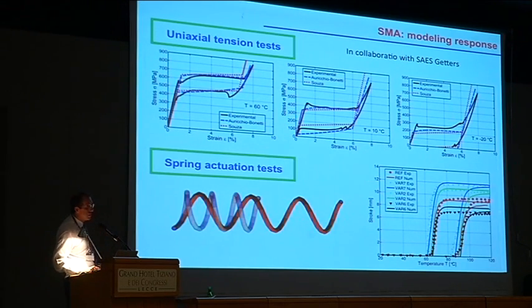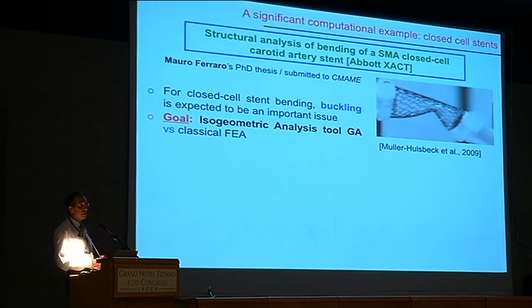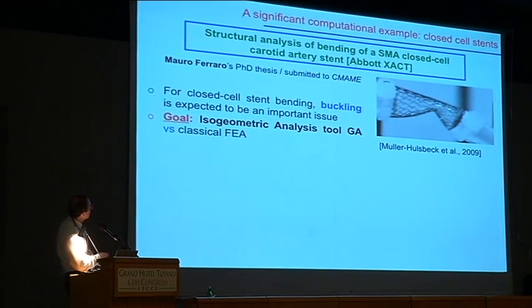But once we have this numerical tool, clearly we got interested in more complex structures. And as I told you, shape memory alloy for us was for very seminal activities. And the first application I've been looking at since a long time ago is stents. So these are grid-like devices which vascular surgeons put inside the human body in many situations. And if you look at the literature, a very common way that stent producers have to test the device is to take the device and bend it. So they simply grip it on the two sides, and then they pull down one side, and they bend the stent, and as you can see here, they have some instability effect. So the goal was to try to build up a numerical scheme for this geometry, which is quite complex, and try to see if we can reproduce this effect.